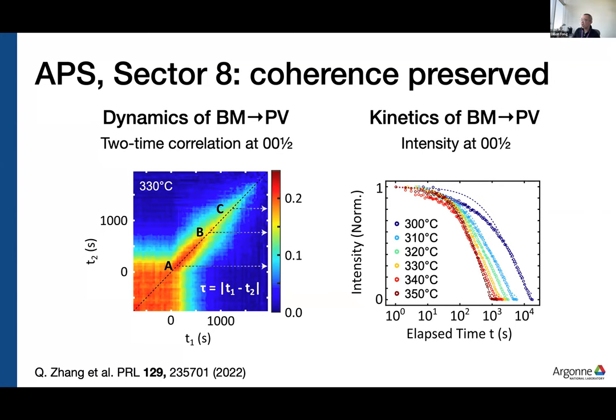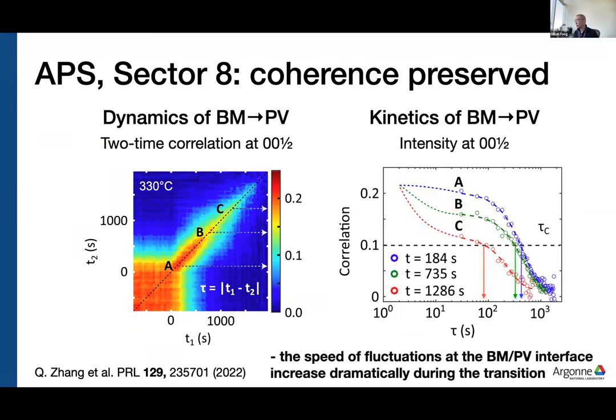The information in the two-time correlation function can be best described by taking these horizontal cuts. So I'm showing a cut at point A, point B, and point C. And so if we look at the correlation as a function of time for A, B, and C, we could just draw some arbitrary dashed line at point one. And then we can say these correlation times tau C are given at the bottom axis. Anyway, you see that from these changes in the decorrelation time, that the speed of the fluctuation increases during the transition.